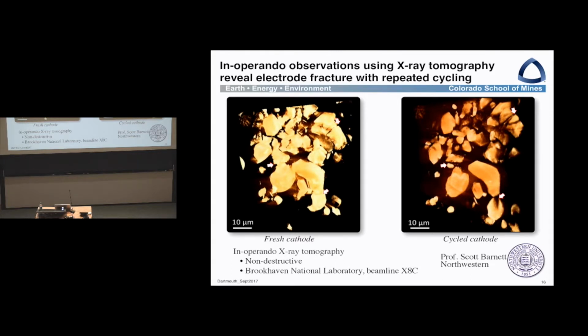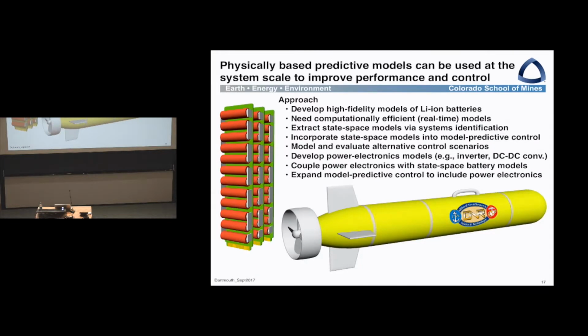That's one of the reasons you have capacity fade in your battery. If this particle splits off and it loses electrical contact, then there's no way to make the charge transfer chemistry run, and that little bit of cathode is basically useless. And if that happens enough, your battery doesn't have the same capacity as when you originally purchased it, and everybody's familiar with that paradigm. You buy a new battery at some point. There are other reasons for capacity fade. That's one. Okay.